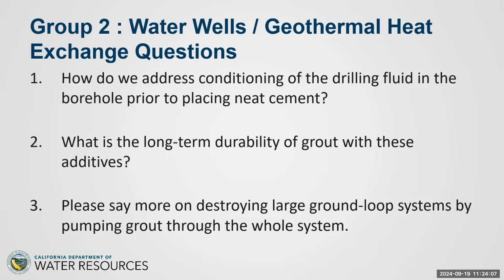I mean, I don't know what the definition of that is, but in a way that wouldn't allow contamination or preferential paths developing. Now, I completely concur. I think what we're seeing is that the one particular agency that required Halliburton to pump the cement in this well didn't have a concept of the fact that they pump very fast, and the whole process was done in minutes as opposed to hours. And so that was the real problem in this situation.